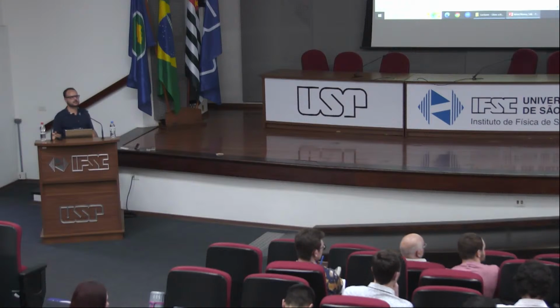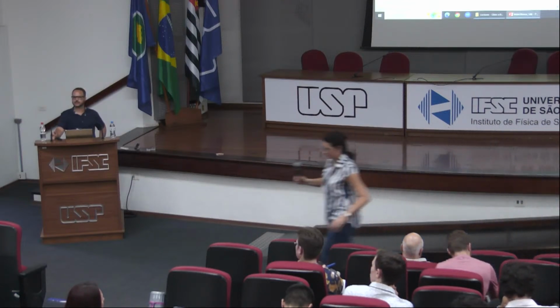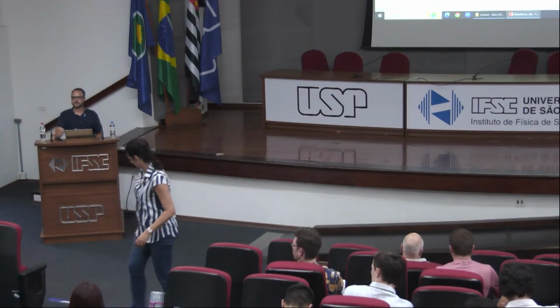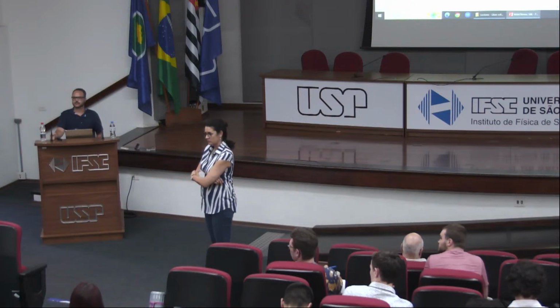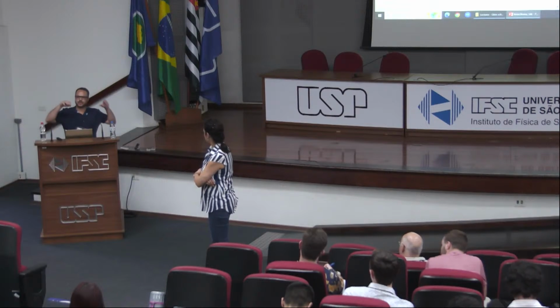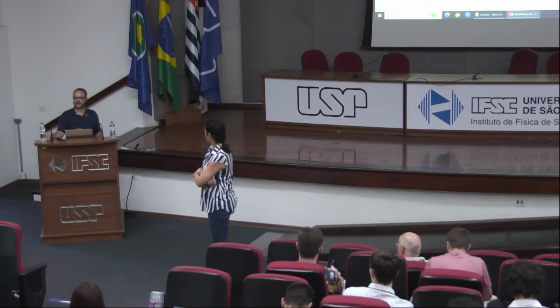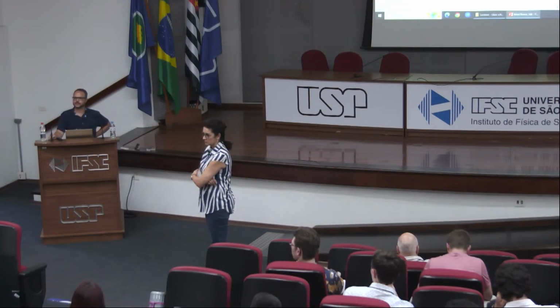Okay, one more question. Thanks for the presentation. I got curious about why homonuclear dipolar interaction is not so important for glasses. Yeah, the problem is that in glasses we have such a strong distribution between environments that most of the time the homonuclear dipolar interaction behaves like the heteronuclear one, because the chemical environments of the two neighbors are different, they are not the same anymore. But sometimes you have to consider it. Yes, sometimes.